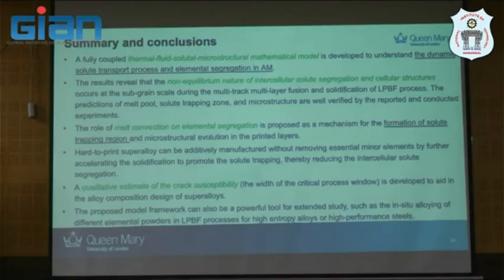This modeling framework is a multi-physics, multi-scale simulation that will be useful for further studies like this one when you want to design a new alloy in additive manufacturing, especially in the case of blended elemental powder. We call this in situ alloying. You alloy A and B, it will be AB or ABC, which a lot of studies do, especially in the high entropy alloy community. They mix 4 or 5 elements together and blend them under the beam. So this is probably a way forward and gives more opportunity rather than doing atomization all the time.